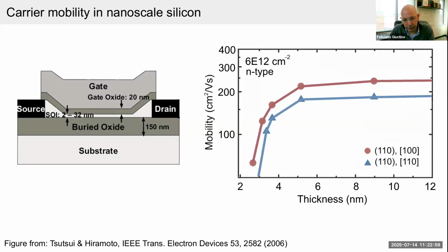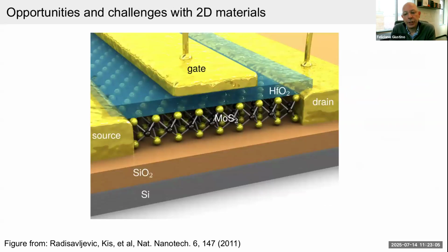So the community that is interested in developing post-silicon devices has been focusing primarily on the possibility of using two-dimensional materials to replace silicon. This is only a cartoon, but it illustrates the main idea. In 2D materials, like van der Waals materials, like in this case, molybdenum sulfide, you can realize these materials in monolayer form, and therefore you can have atomically smooth surfaces. And there is the hope that because of that, the interface scattering may be suppressed, and therefore you might still have reasonable mobilities without experiencing the degradation that people see for silicon.